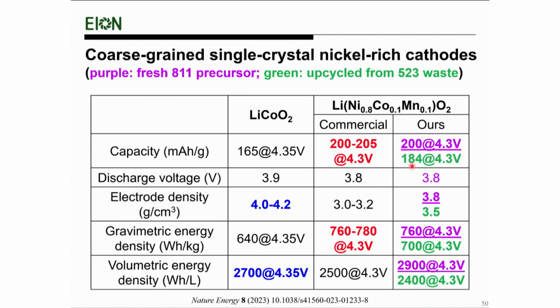But using the upcycled waste, we're able to get still not perfect, but pretty decent gravimetric capacities. And because we are single crystal, we're able to reach a very high compressed density, electrode density as well. So overall, we're able to get a volumetric energy density of the upcycled material that's close to the commercial material. And we're even moving beyond the 811, we're moving into the lithium-rich and manganese-rich single crystals, and we can produce those materials with capacity more than 250 milliampere hour per gram.